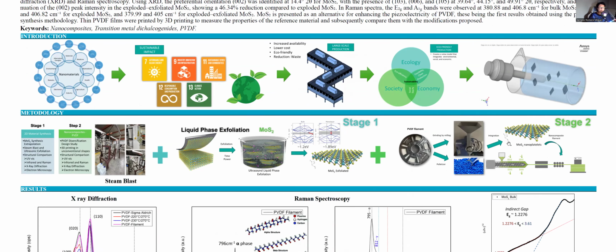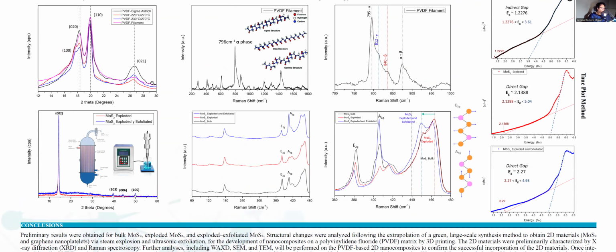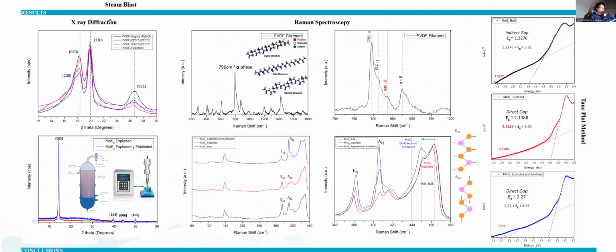The second stage is to incorporate the PVDF and the molybdenum disulfide to obtain the nanocomposites as an extruded filament, and finally to print this material in non-conventional forms. So as results and characterization for PVDF, which is the first part, we did X-ray diffraction and also Raman spectroscopy to see in which structure or phase we were working with the precursor material.